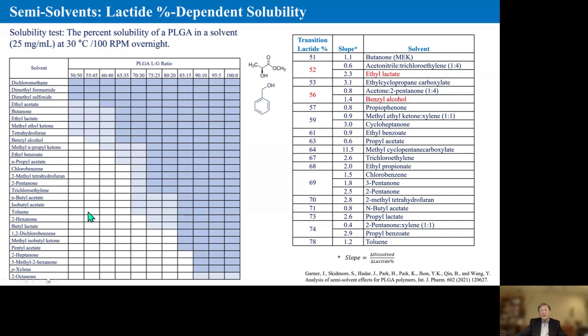So basically, if two polymers differ, one dissolves in toluene and the other does not, they are basically two different polymers. So even though the name PLGA is the same, based on LG ratio, they have totally different properties. On the right side of the table, for example, let me show you 56. This means the transition lactide percent, 51% all the way to 99%. Now, in this particular example, benzyl alcohol has a transition lactide percent of 56%, which means that if the lactide content is 56% or higher, then they dissolve in benzyl alcohol. But if it's lower than 56%, the PLGA does not dissolve in benzyl alcohol. So there are different solvents that we can choose.